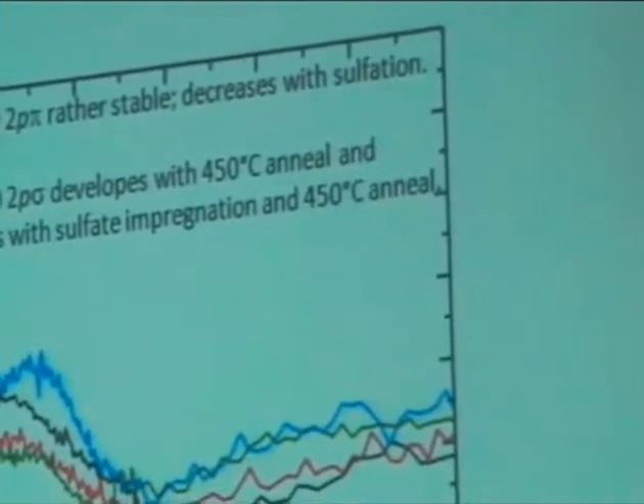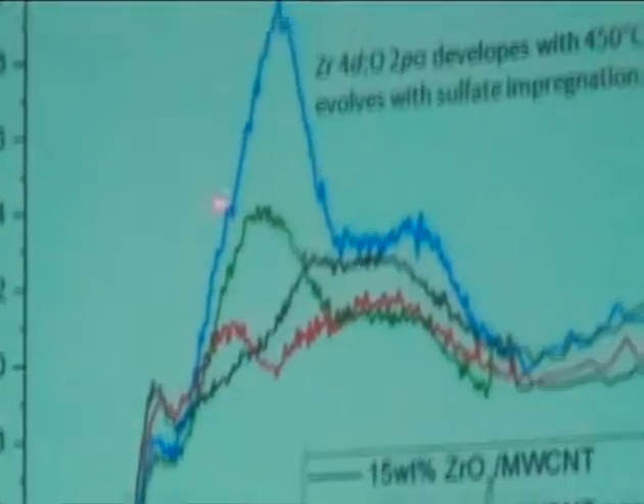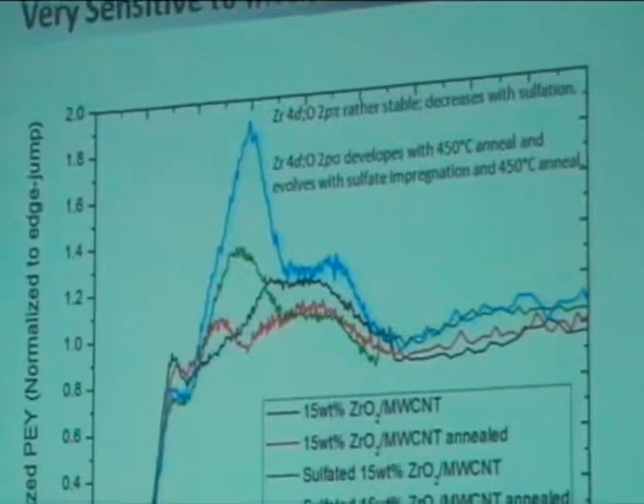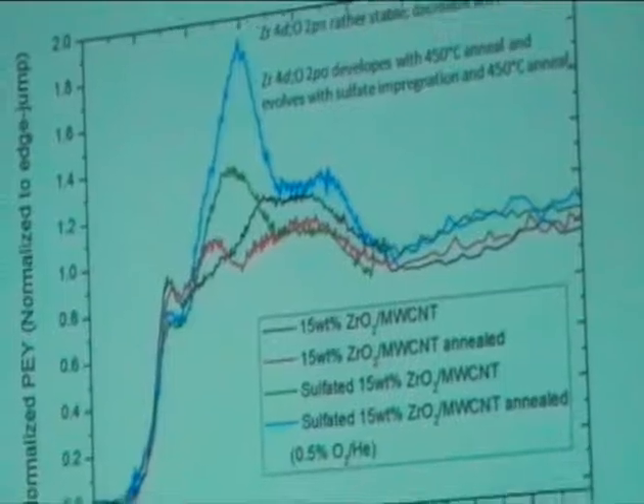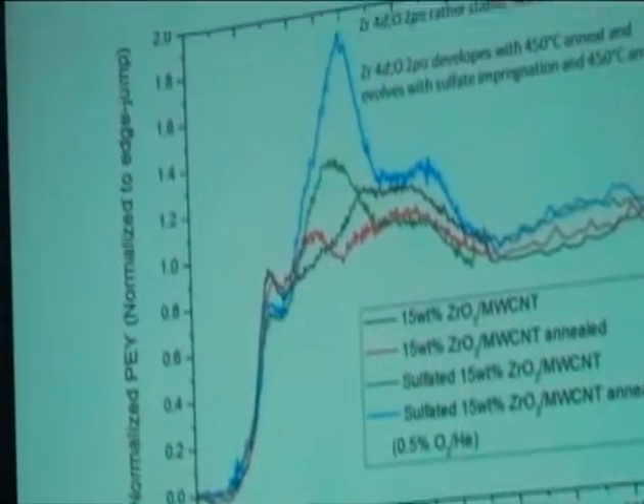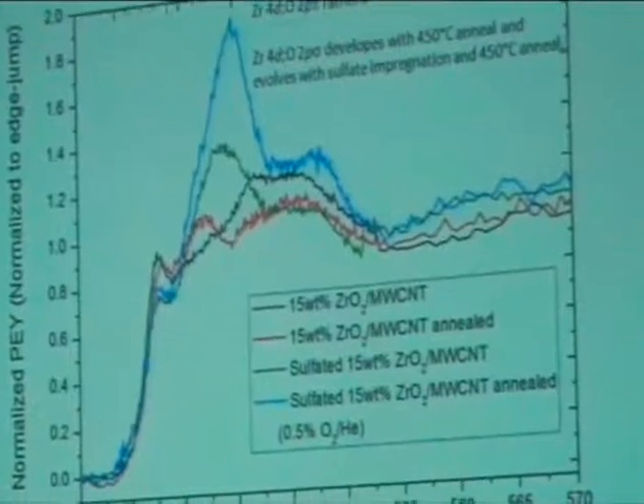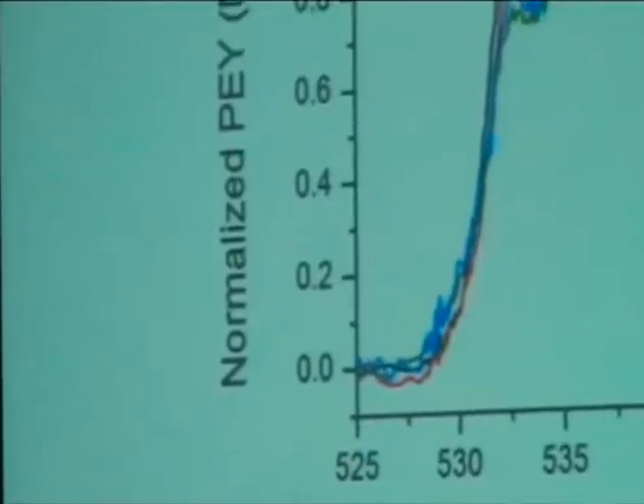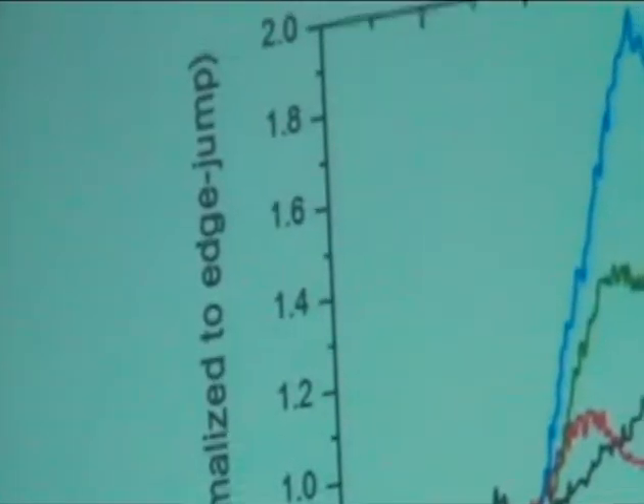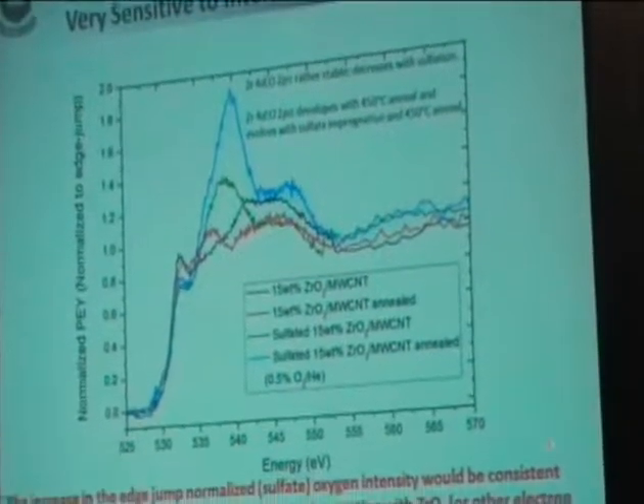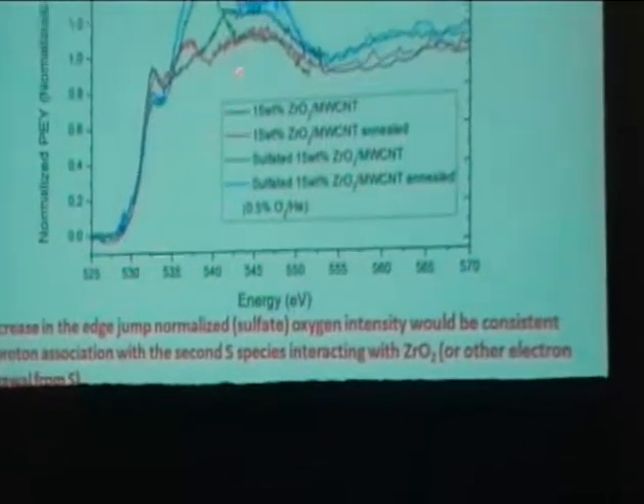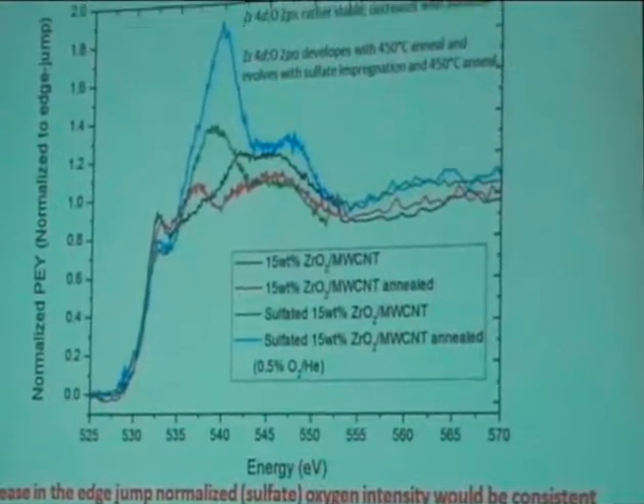And these are normalized to the average oxygen medium. This is the average oxygen electronic environment that we're looking at. And so this increase in intensity is due to less average electron density on the oxygen in the pi star peak. When that happens, it could be a consequence of that proton withdrawing electron charge, but in fact, it can be any other electron withdrawal that happens at the sulfur during this annealing. But one possibility is it's the fact that that species has associated with a proton, which is withdrawing charge.